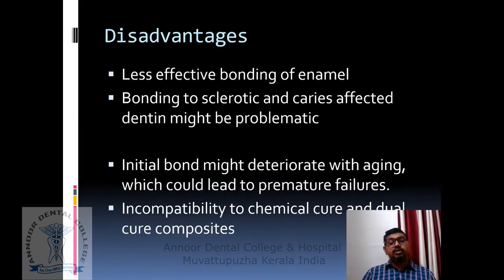But it comes with a few disadvantages also. One, the strength of the acid in self-etch systems is much weaker compared to your etch and rinse systems. So the bonding efficacy to enamel is going to be less, because the acid may not be able to effectively etch the enamel. Then bonding to sclerotic and caries affected dentin also may be less effective. Then the third thing is there can be bond deterioration with aging. Even though the initial bond strength is satisfactory, it can lead to premature failure.